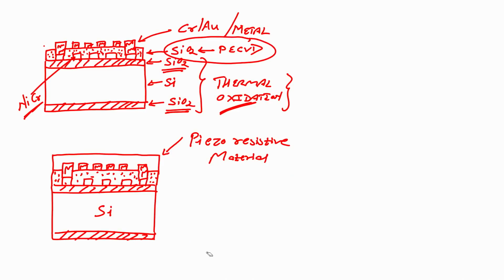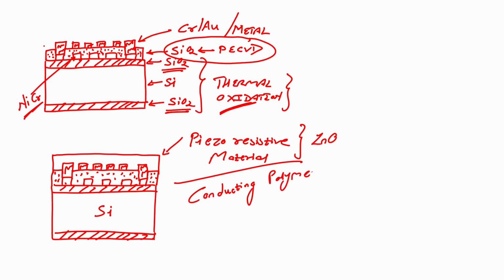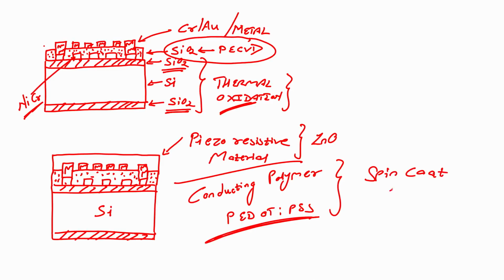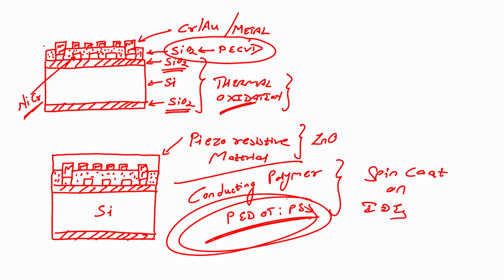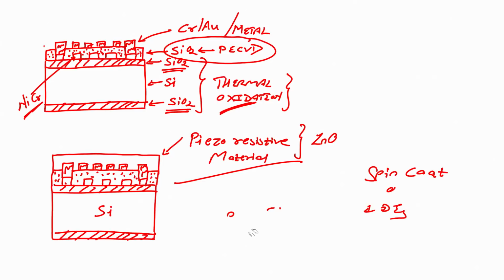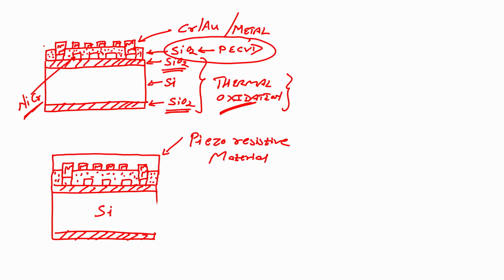Okay. Now, there is an alternative material which is a conducting polymer. Now, this can be zinc oxide, right, or any other piezoresistive material, but if I want to use conducting polymer, generally polymers are non conducting, but if I want to use conducting polymer, I can use PEDOT:PSS, and for using PEDOT:PSS I have to spin coat it on interdigital electrodes. This is also piezoresistive material. Okay. So, point is that we will deposit or we will spin coat piezoresistive material, right, using either PVD or using spin coating, right.